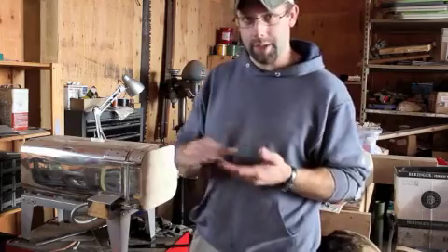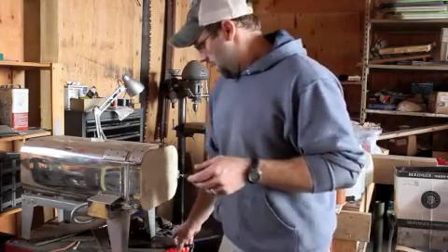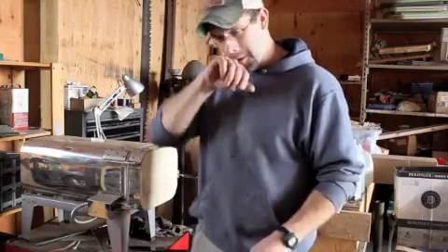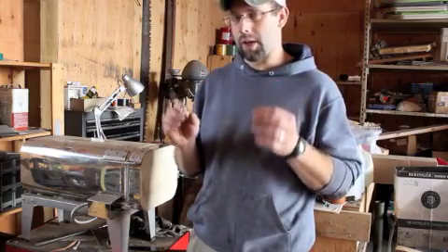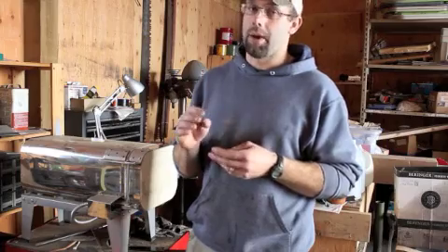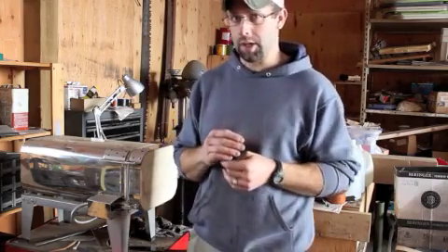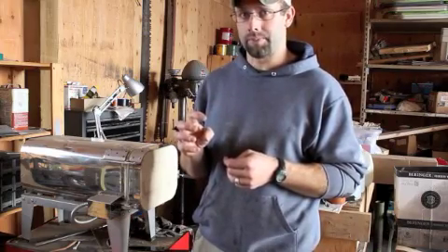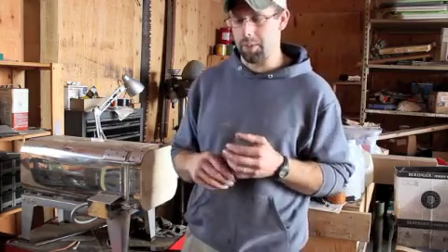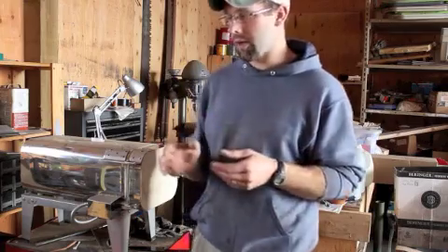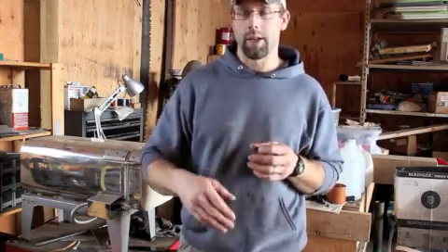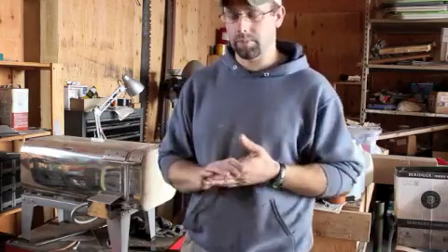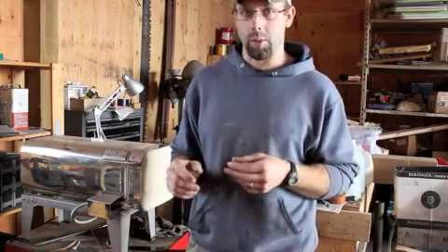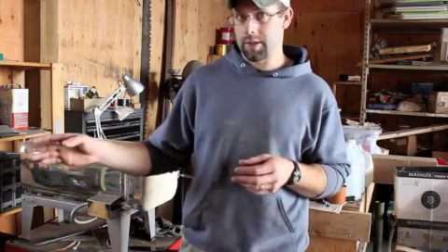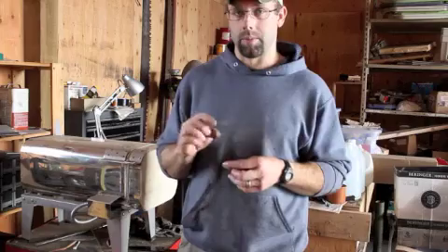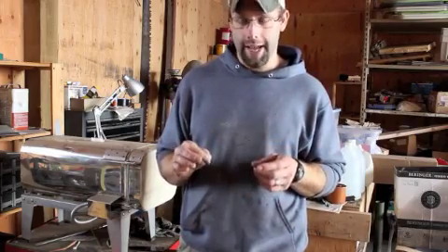So once you forge your knife at the forging temperature, and depending on the steel it varies, I forged this right around 1700 degrees. Once you do that, you run into another issue, and that is when you forge at the proper temperatures, which is higher temperatures than normal heat treating, you have enlarged the grain structure of the steel. And that's not good, because that does not give your steel the most strength and toughness that it can have. So if you go straight from forging temperatures and your blade cools down, and then you heat it back up to heat treating temperatures and go from there, you're going to have a problem. You're going to have a lot weaker blade than you would otherwise. Even if you buy a good piece of steel from a supplier, you're going to greatly decrease the quality. So here's how you fix that.